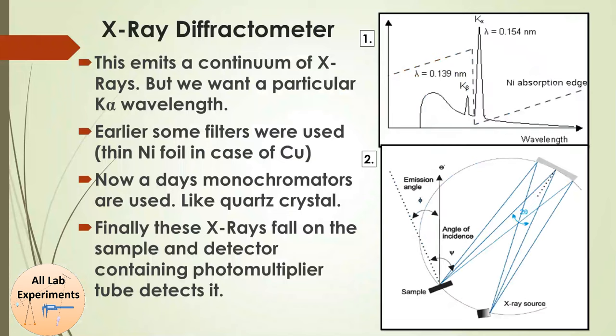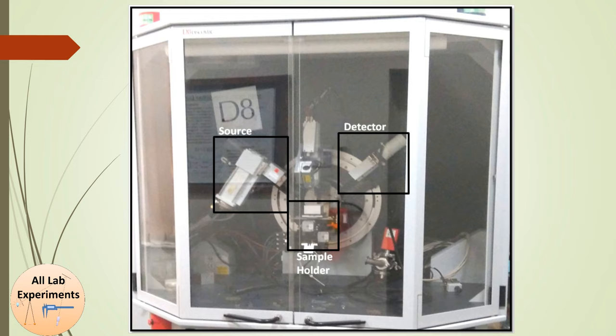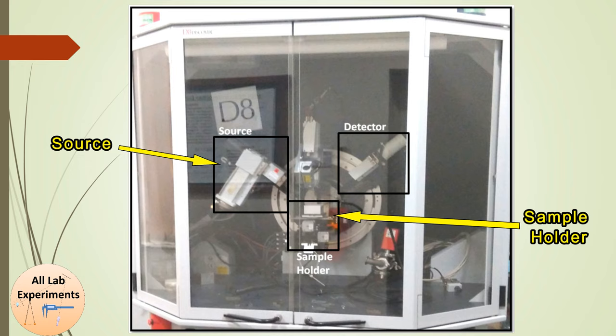In figure 2, there is one X-ray source emitting X-rays onto a spherical piece of quartz. This system is set so that for copper Kα emission, the crystal obeys Bragg's law and emits only copper Kα radiation — lambda equal to 0.154 nanometers — which is used for sample investigation. In the next image, a typical X-ray diffraction machine is shown, with an X-ray source, a sample holder, and a detector that records the diffracted X-rays.